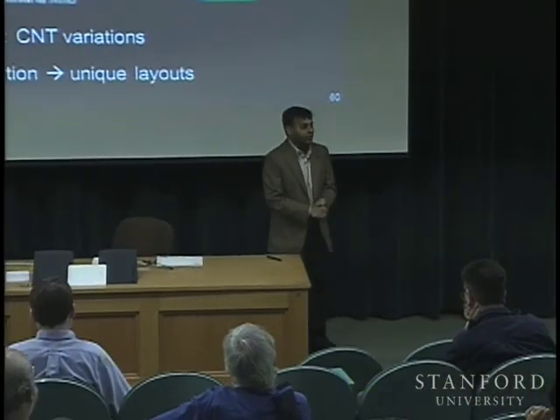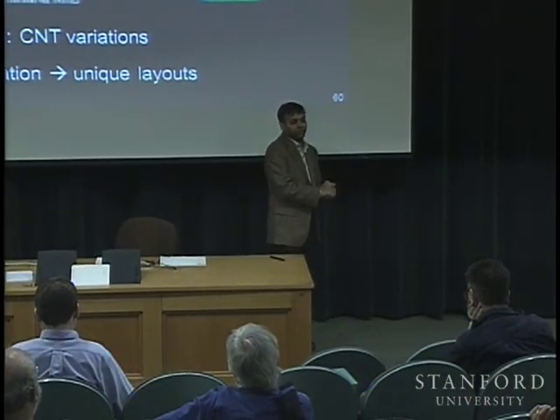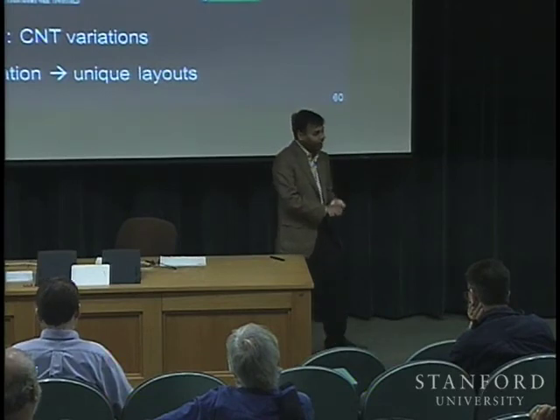Anybody else? Of devices that people actually make, what's a typical number of carbon nanotubes? Right. So, I would give you the number in terms of density. How about that? Typically when we grow carbon nanotubes in our lab, on a really good day, if you are lucky, we would roughly see something around maybe 5 nanotubes per micron. Remember, we have to achieve 200 nanotubes per micron.